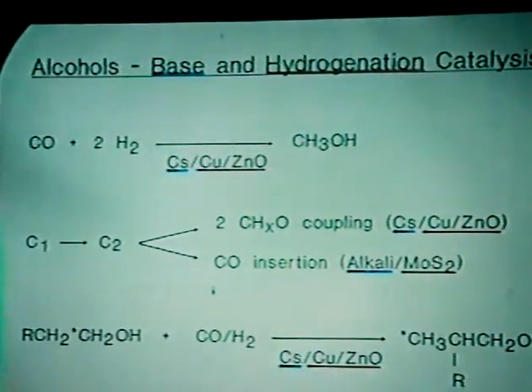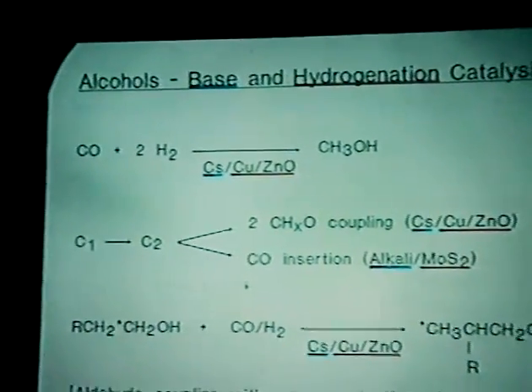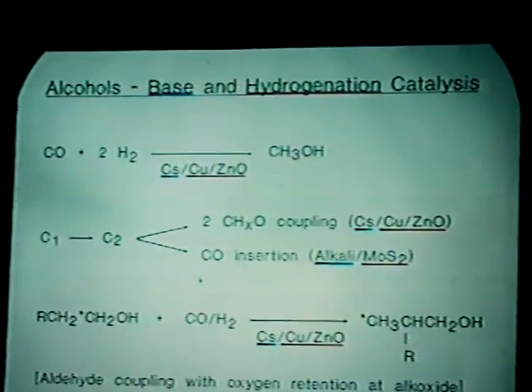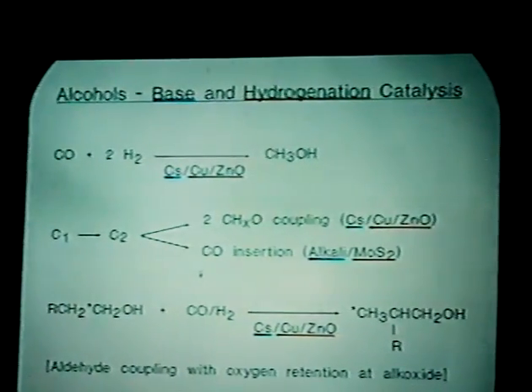In the hydrogenation and base catalysis, I believe that the bifunctionality clearly is originating from the chemical principles that are brought about by the heavy alkali. The light alkalis don't do it. It's very clear that the counter ion of the heavy alkali is the most basic that is needed for all this catalysis.